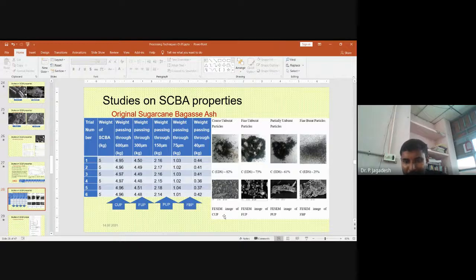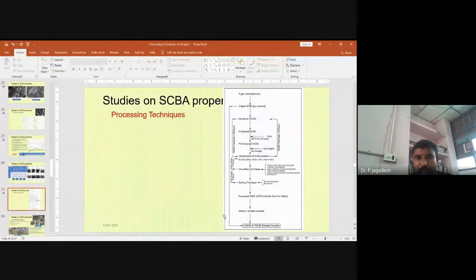The presence of carbon content is drastically reduced. At the initial stage itself, you can remove a large amount of carbon content by normal sieving. You can see this using EDX analysis, sometimes called EDS, that is energy dispersive spectroscopy. You can see a drastic reduction in carbon content for fine burned particles. Based upon the size of the particle itself, your particle's carbon content is reduced.